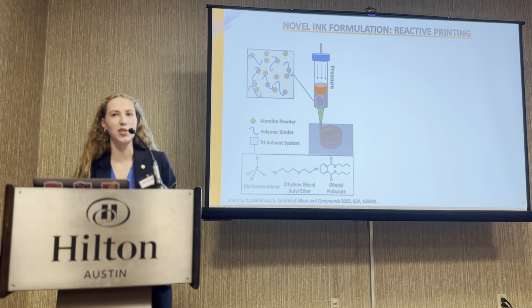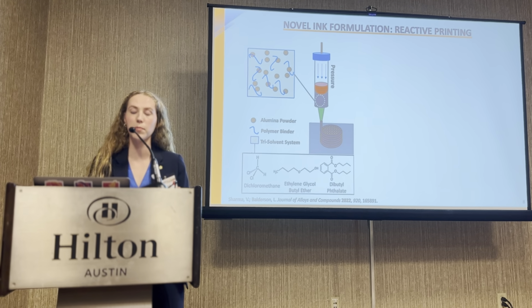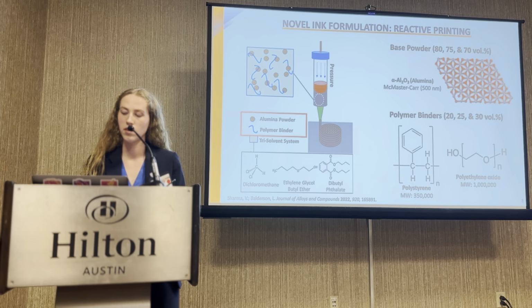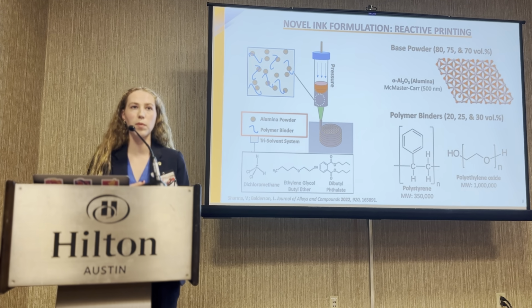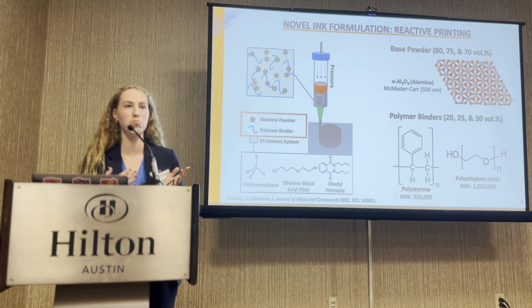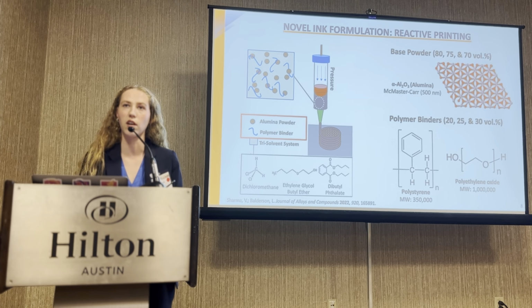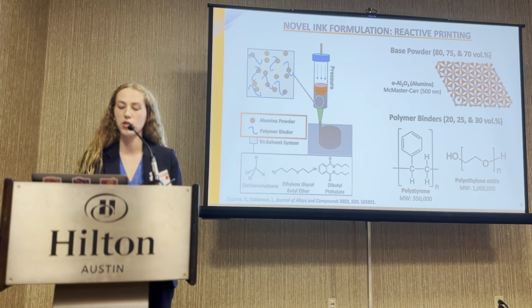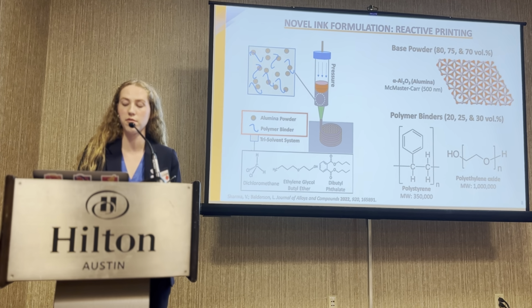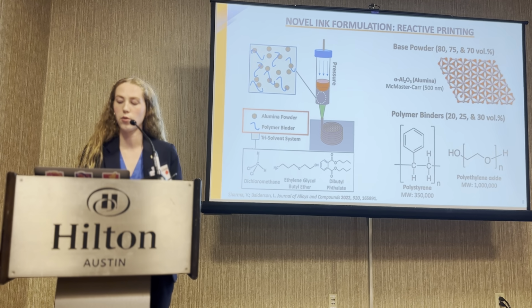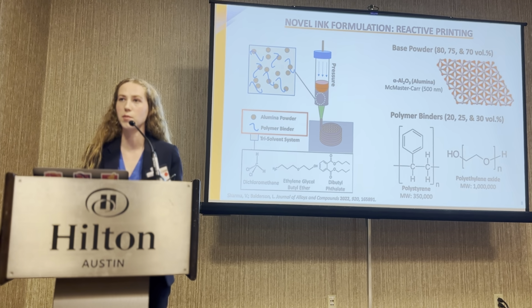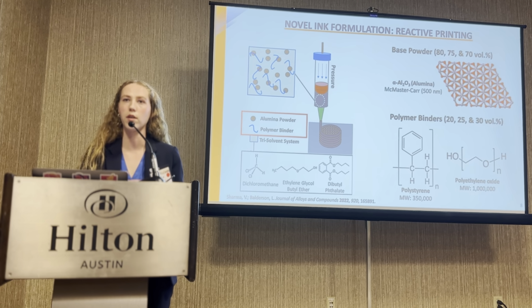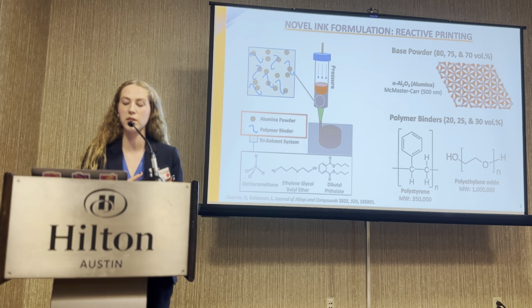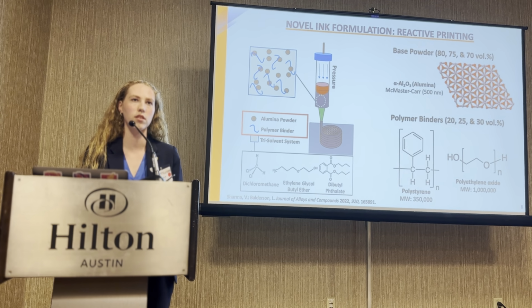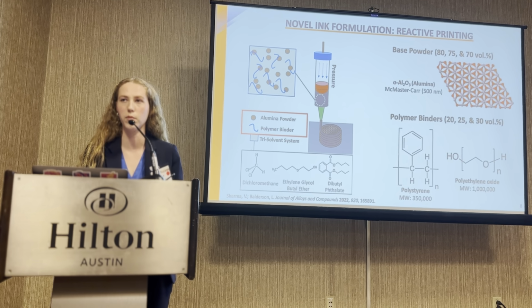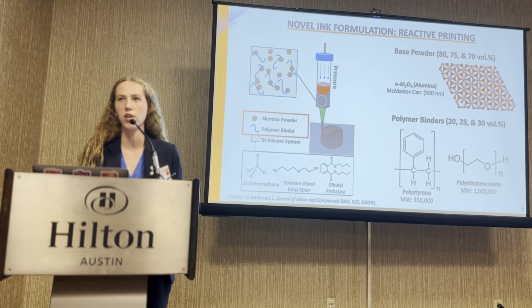So the ink formulation. The two main components are the ceramic powder and the polymer binder. We experimented with a base powder. We started with alumina because it's super common in literature and it's a great stepping off point. And we chose the ratios of 80, 75, and 70 volume percent in order to get the maximum density possible in our sintered prints without limiting the performance of the ink.